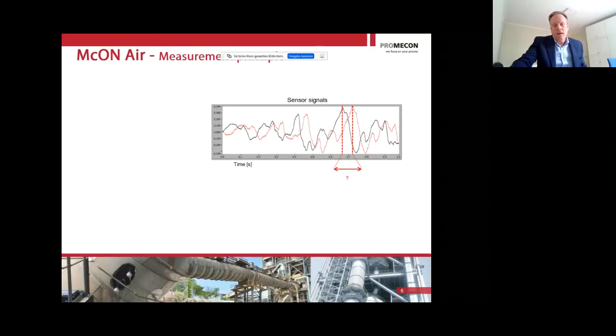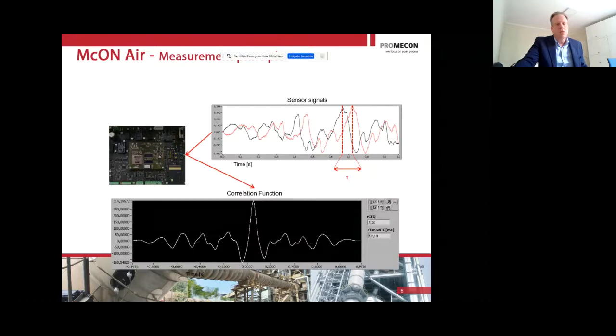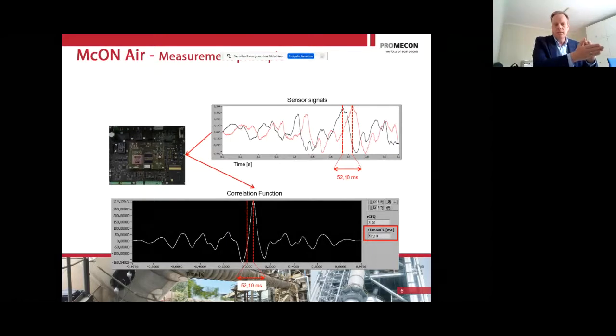And here comes the digital part of our measurement. We have these signals that we record, and then we put them into a digital algorithm, a so-called cross-correlation function. And this cross-correlation function will shift the two signatures until the point that they have the best match, right? So we have a calculation of time shift, and the cross-correlation function will tell us the maximum of the function is at, in this case, 52.1 milliseconds. So what our two sensors are doing is they're giving you a time shift. How long does it take the gas to get from one sensor to the other?